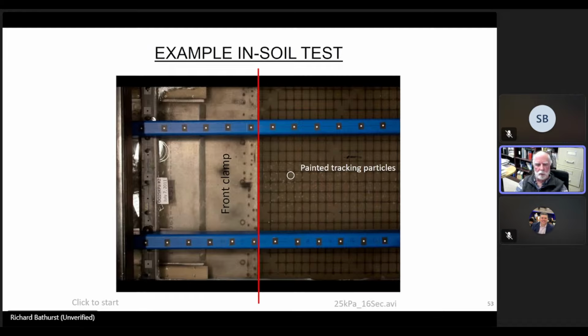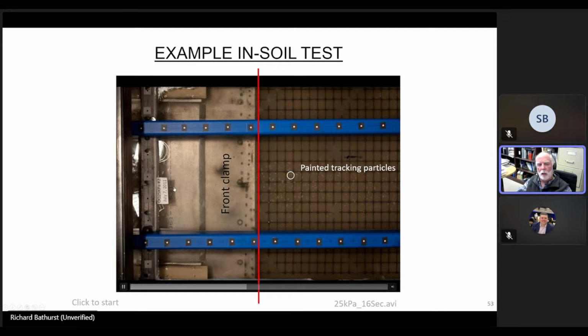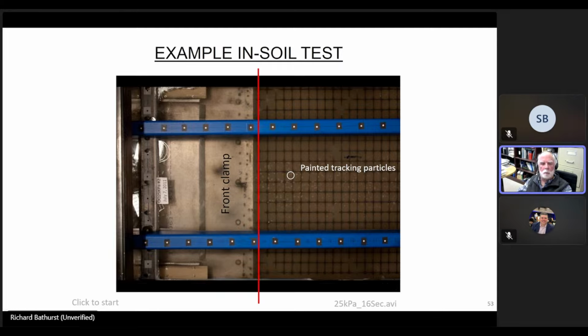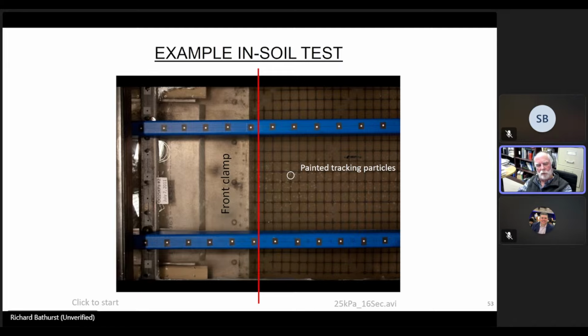And what you're looking at in this photograph is, you imagine you're lying on the floor underneath this pull-out box and you're looking up and you can actually see the grid and some painted tracking particles. So this is the pull-out specimen, and this is a front clamp which pulls the reinforcement through the transparent soil. And keep your eye on the red line for point of reference. And what you can see is, as the reinforcement is being pulled towards the left, you can see it stretching. Okay, and stretching. And finally, at the end of the test, the reinforcement actually breaks.